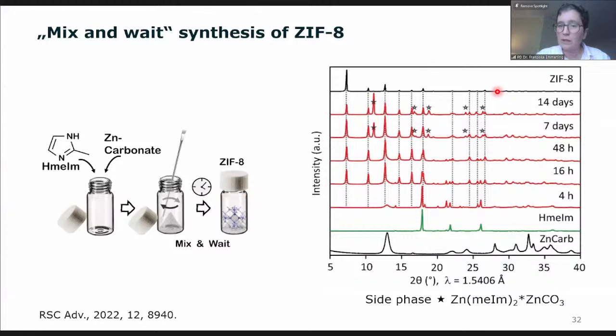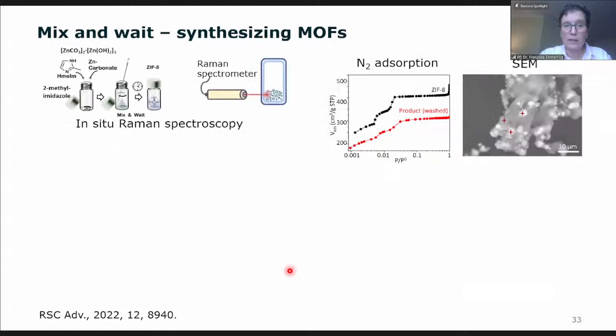So if you look at the position of the reflections, they agree. The intensities do not agree. That has to do a bit with the leftover material still stuck in the pores. But after some activation step, you end up with a neat ZIF-8 pattern. If you wait too long, then you see the formation of a side product. So the little stars here, that is because we are producing a bit of CO2, and that reacts further with the linkers. Again, we were interested in what's going on, and we performed here in this case Raman in situ measurements.